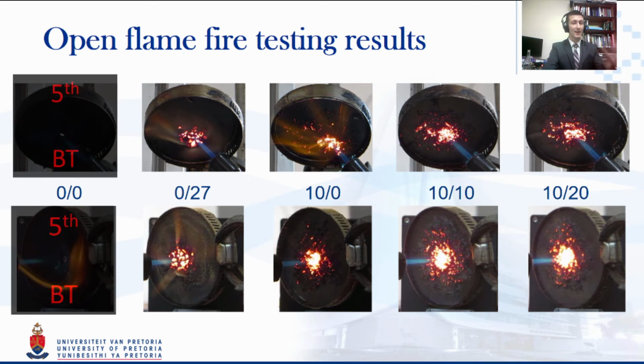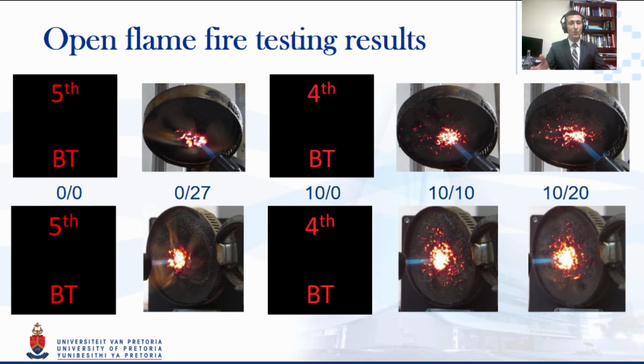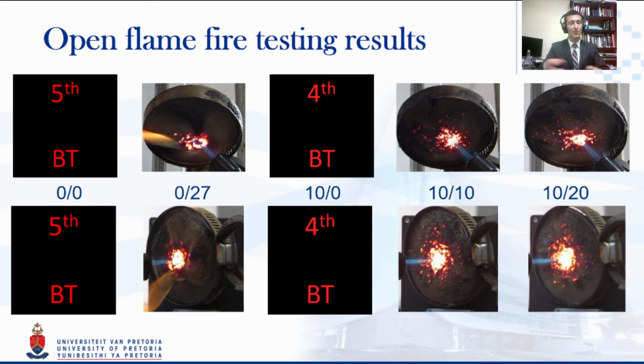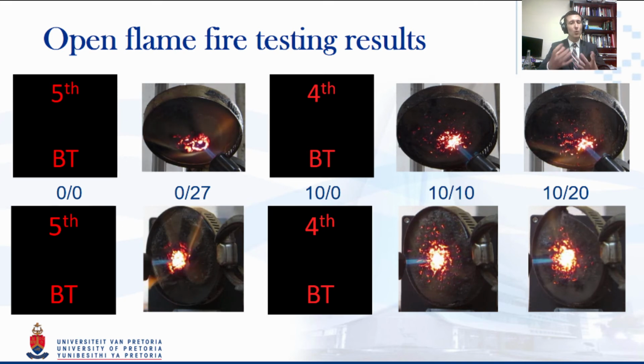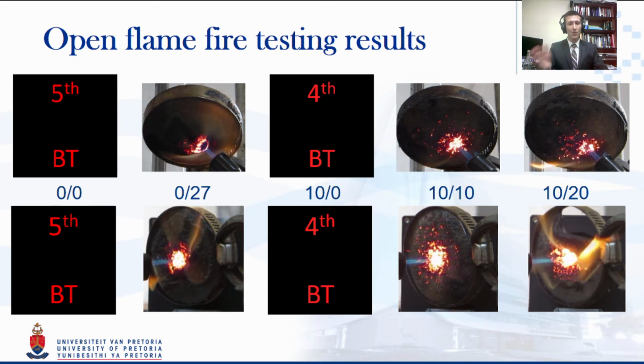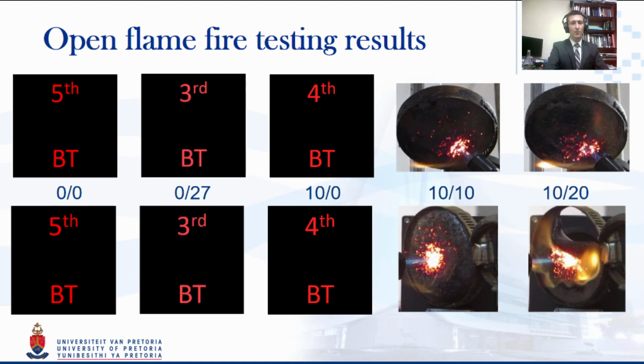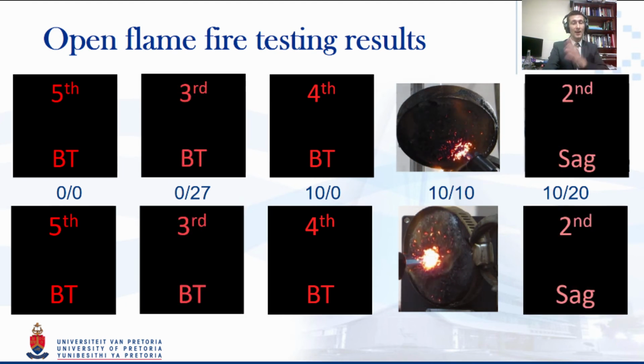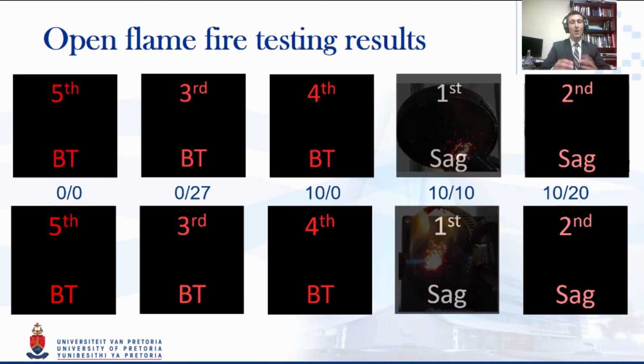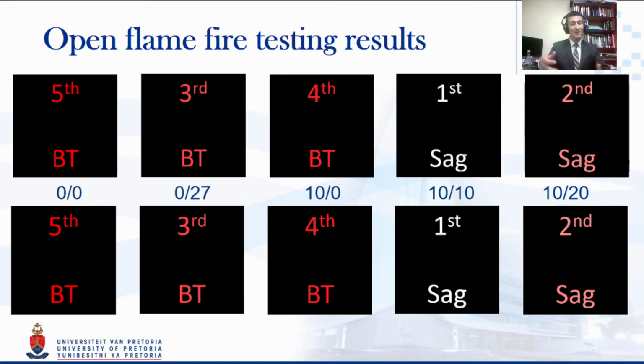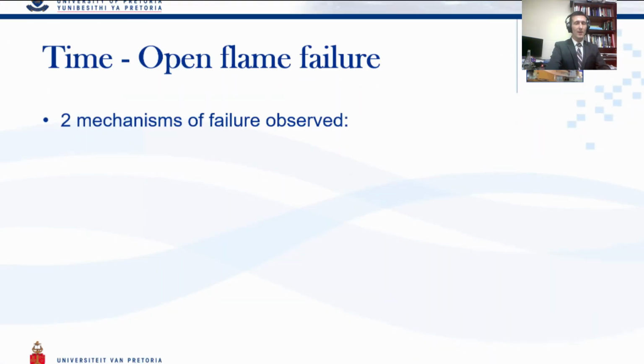So the worst and the quickest via burn through was in the neat material. Whereas the second one, which actually started burning quite a bit, was the expandable graphite itself, because the strings are a bit more readily available to burn. But here in the other ones, there is some really good thermal behavior, such that in the eventual best products, only once the material reaches a melting temperature and sags does it actually undergo failure, and burn through does not actually occur. So I'll show that on the next slide.